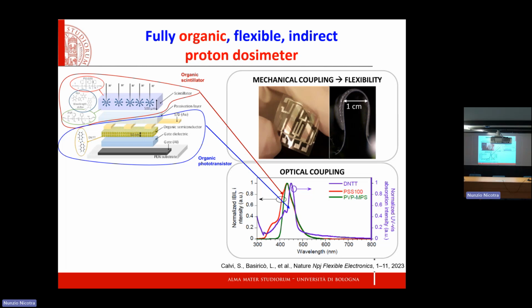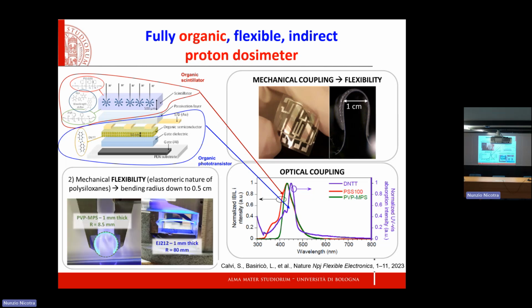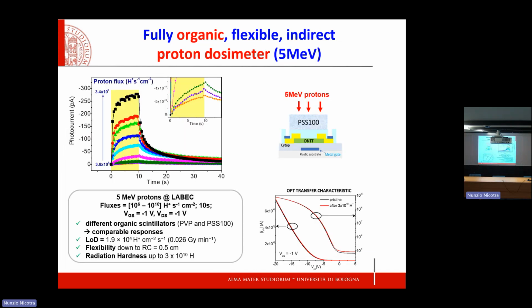So you couple them together, and what you see, this is the scintillator, the plastic thicker layer, and this is the phototransistor. You really put them together and obtain a very nicely bendable device, which is much more bendable than what you would obtain with scintillators that are still plastic, but not specifically developed to be flexible. Okay, so there's quite a lot of work that has to be done.